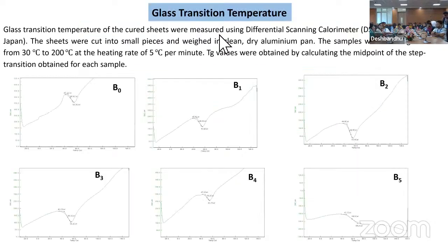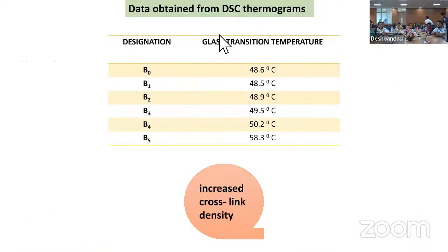We have also determined the glass transition temperature for all the films, and these values are also compared here. For B0, it is 48.6. There is a slight increase in glass transition temperature. So these data strongly support that our monomer, which has amide linkages and a primary alcoholic group, is participating in the polymerization reaction.